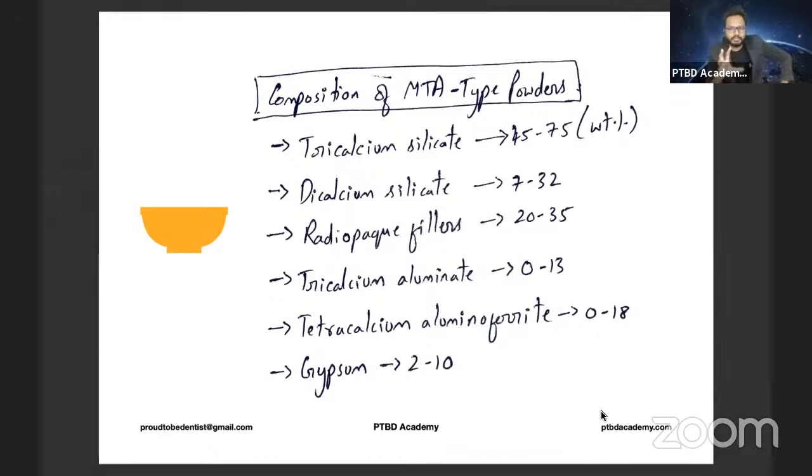We're talking about MTA powder before you hydrate it. It's not an acid-base reaction. It's not polymerization. It's simple hydration of cement. You just add water, obtain a putty-like consistency, that's it, and use it for clinical purpose.